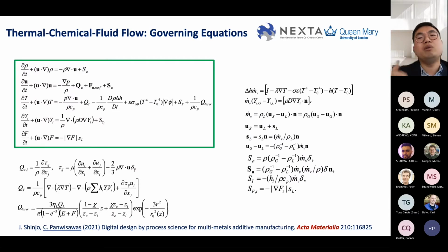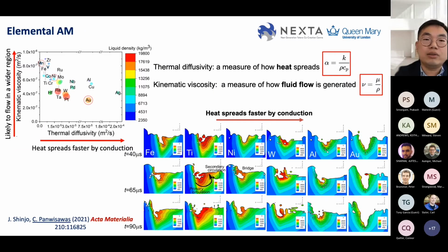Having said that, we want to extract some chemistry process characteristics using the thermochemical fluid flow framework that we proposed in this Acta Materialia paper. I don't want to go much into the detail of the equations. If you're interested, please go and review some of the equations there. But more interestingly, we see some trend in these transition metals. If you look at the kinematic viscosity versus thermal diffusivity, thermal diffusivity definitely measures how heat spreads onto your bed if you use a powder-based fusion process, for example. And kinematic viscosity measures how fluid flow is generated.